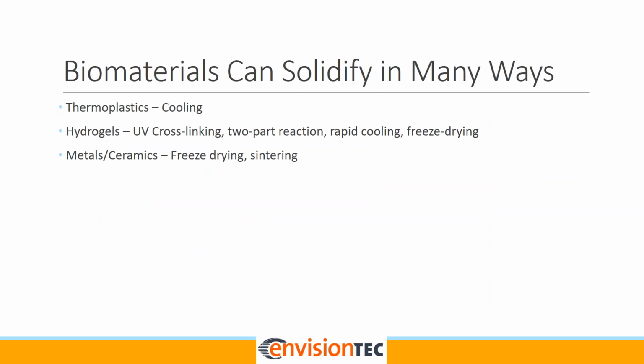So then, whether you're using a hard or a soft biomaterial, we have to take it in its raw form and then solidify it in some meaningful shape. So with thermoplastics, you can heat them up, melt them down, and cool them. With hydrogels, there's many different ways of solidifying them: UV cross-linking, a two-part reaction, rapidly heating and then cooling them, and even freeze-drying them. Metals and ceramics must be held together with some sort of viscous binder, and then once the weak construct is made, you can sinter it or freeze-dry it in an oven.